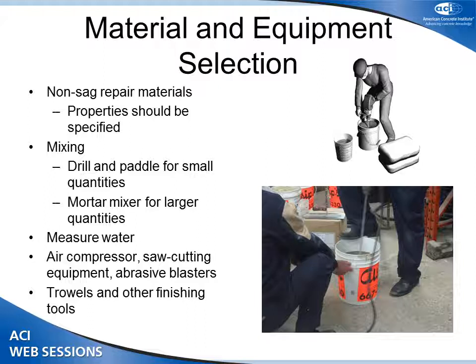In addition to the non-sagging characteristics, there's a whole list of properties that could be specified by the consulting engineers, anywhere from different types of set times to important properties such as shrinkage of the material, freeze-thaw resistance, etc. So those properties should be specified by the consulting engineer or the owner. Mixing the material: since these are typically small repairs, it's very common to mix one-bag quantities at a time. So you're generally going to use a pail with a drill and a paddle mixer. If you have a lot more quantity of repair to complete, you can use small mortar mixers as well.